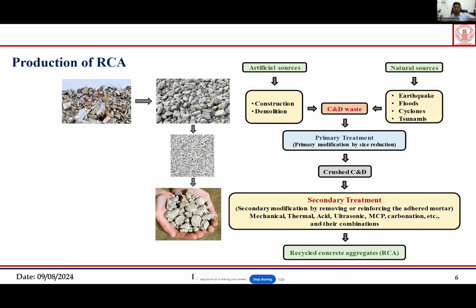Then we do the primary treatment. It means we break it down into some manageable pieces, which you can see in the second figure. Then from there we get the crushed C&D, construction and demolition waste. Then the secondary treatment takes place. It means we try to remove the layer of that adhered mortar, because that is the problem, or we try to reinforce the layer of that adhered mortar in its place. So that is how secondary treatment takes place, and finally we get the recycled concrete aggregate out of it.